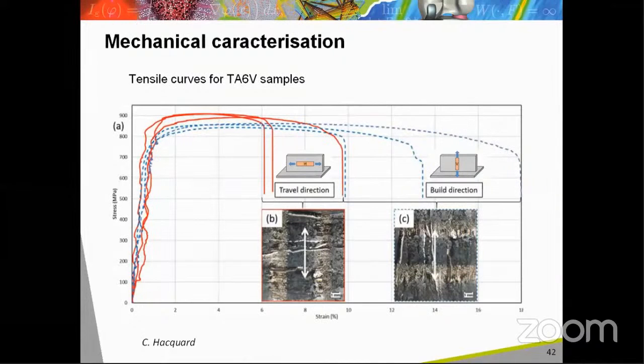One can see on this slide the tensile curves obtained on samples of titanium alloy TA6V produced with the WAM process. The tensile behavior of the materials is different when the tensile specimen axis is the vertical direction, corresponding to the build direction, or the horizontal direction, corresponding to the direction transverse to the building direction. In the case of these materials, the yield stress is higher in the horizontal direction and the elongation is lower. This behavior can be correlated to the columnar grain structure, producing a higher strength in the direction of the grain thickness compared to the direction of the grain's length.